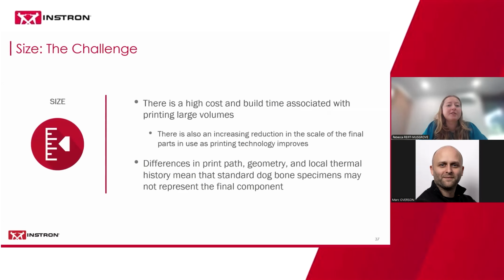And finally, we move on to size. So with additive manufacturing, not all good things come for free, unfortunately, and there is a very high cost and build time associated with printing these large volume additively manufactured parts. Additionally, we also often see parts that are pretty small. We're seeing a real reduction in the scale of the final parts that we're using as the printing technology itself improves. I've gone to fairs where I'm seeing small additively manufactured parts that are really accurate to the micrometer.